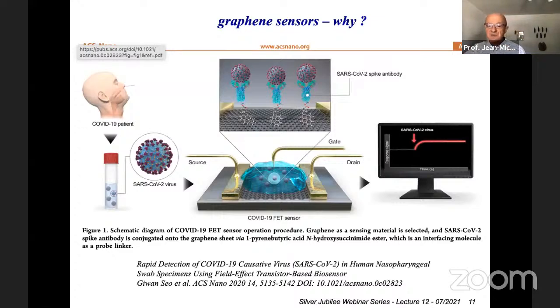But the most interesting property used for graphene photodetection is one which also makes it a good sensor. When you have different kinds of electron acceptors or electron donors on top of a layer of graphene, you can shift the Fermi level into the conduction band or into the valence band. You can switch the conductivity of the graphene simply by putting on top something which has any kind of interaction with the graphene.